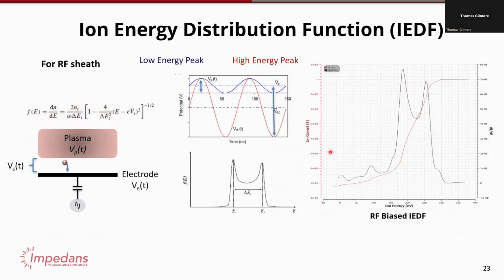If you apply an RF bias, it's a bit more complex. The idea is you have a varying electrode bias, which is plotted in this diagram. The red line here is the electrode potential. The blue line is the plasma potential, which doesn't stay constant, actually. The plasma potential will also oscillate with the applied bias. And then sometimes the difference between the plasma potential and the electrode potential is small, and sometimes it's very large. The result of this is some ion energy distribution function, usually with some peak splitting. The splitting depends on the mass of the ions involved and the frequency involved, like how much the ions can respond to the applied voltages. If they're too heavy, they're basically going to see an average bias. But if they're lighter or if the frequency is slow enough, they will follow along this voltage and you get wider peak splitting. So this is a typical distribution that you see there.